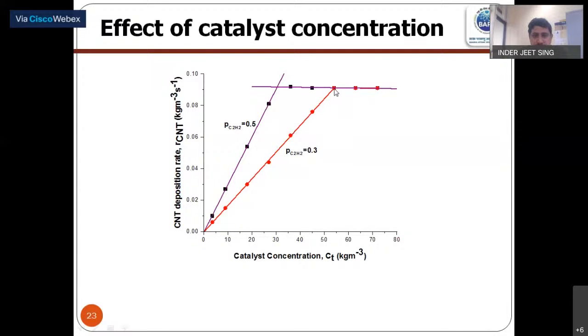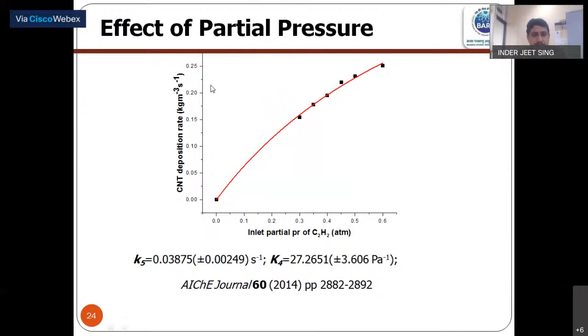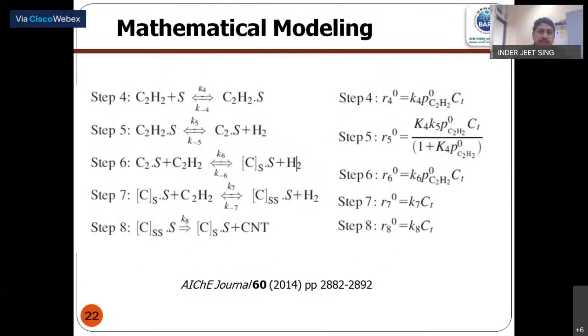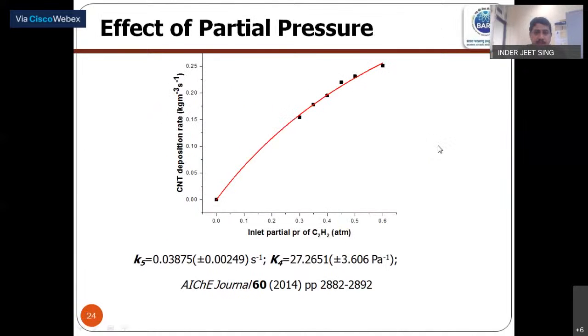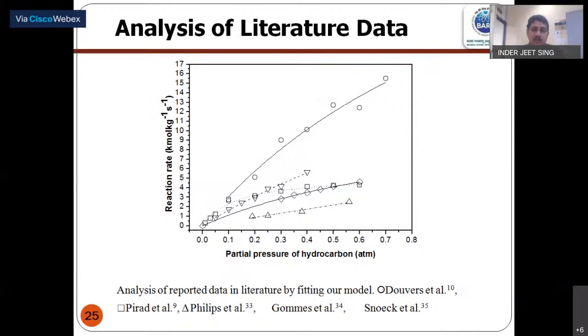Finally we achieve some saturation value. And when we plot the CNT deposition rate with respect to partial pressure and try to fit it, we can see that it fits with this fifth one. This fitting is the best fitting, and from there we can tell that the fifth step, the dissociation of adsorbed acetylene into the carbon molecule, is the rate controlling step for CNT growth in a fluidized bed process. Here we can also find the rate constants, and we have published this in the AIChE Journal. Also, we analyzed other published data with our model, and we found that our model could predict the others' data as well.